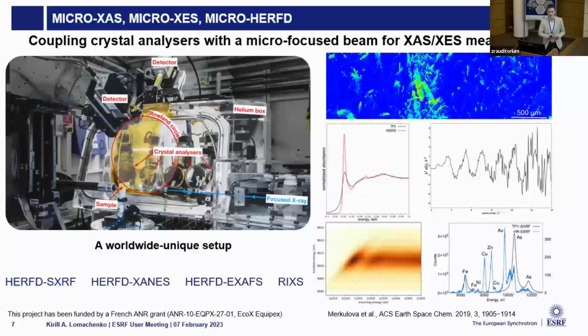The first one is the micro-XAS, micro-HERFD setup that couples the micro beam, so the submicron beams that we can achieve by KB mirrors, with a spectrometer with 5 analyzer crystals. So we can measure, thanks to this setup, with high spatial resolution. It's most useful for samples where you need to do mapping with a high spatial resolution, but you also need to discriminate between many different elements present in your sample. You have to discriminate their emission lines, and be able to get the data with high spatial resolution but also high energy resolution, measuring particular elements.